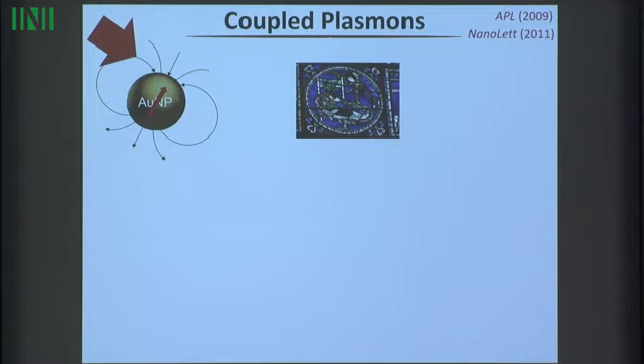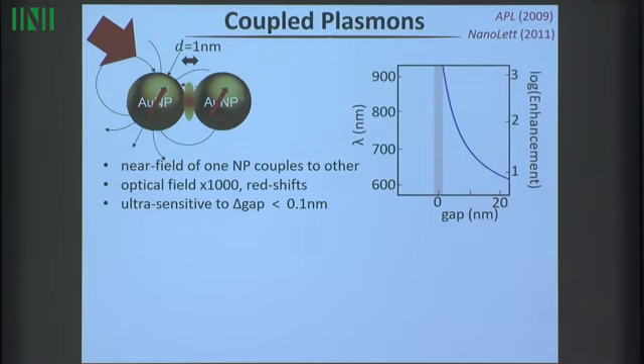But this was not known about for 20, 30 years, and what we're interested in is actually concentrating the optical field. And here you can see the field lines from the oscillating electrons. They are more concentrated at the two poles here, but they're not that concentrated. What happens that's interesting is when I bring another particle close by, then this near field, as well as the light that I'm shining onto the system, will affect the electrons in this particle. And they'll oscillate in a way that then affects the electrons in this particle. So there's a very strong interaction in the system. And it's a bit like a dipole-dipole interaction. It's a classical interaction, like two bar magnets, which you can feel when you bring them very close together, have a strong interaction.